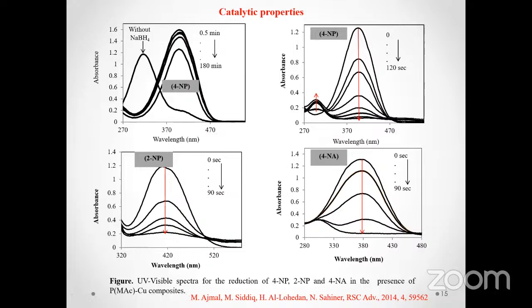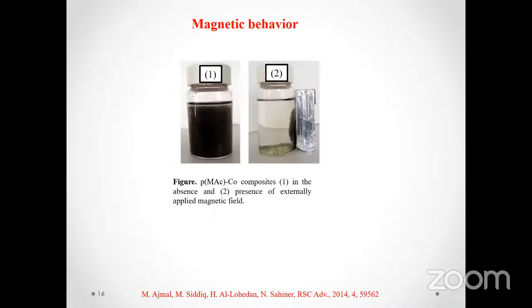So this is how these catalysts can be effectively used for the reduction of water pollutants, and the same was observed in two other water pollutants or nitro compounds: in case of 2-nitrophenol, it was degraded within just 90 seconds, and nitroaniline was also degraded within just 90 seconds.